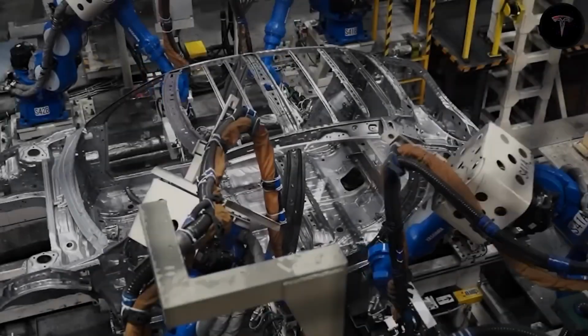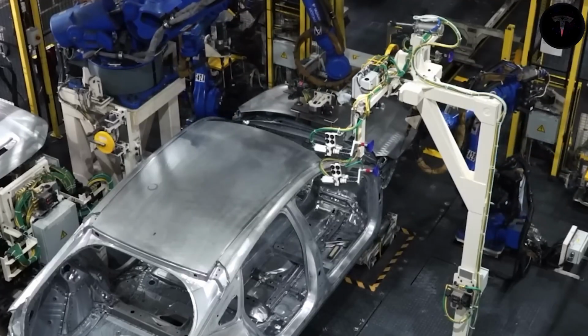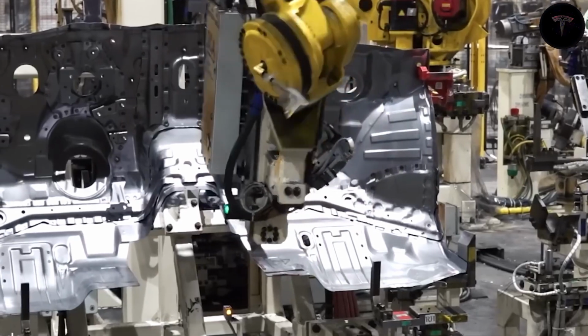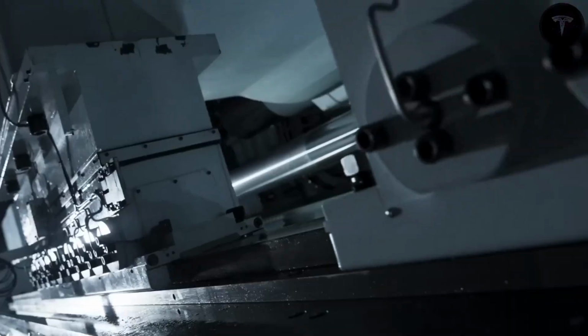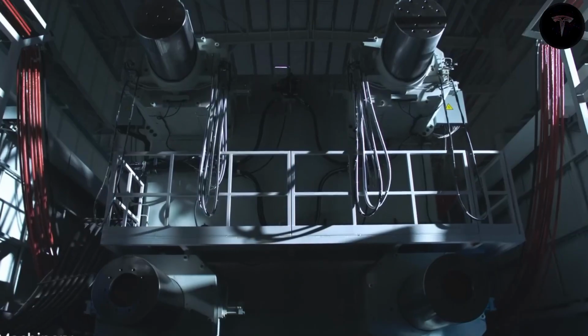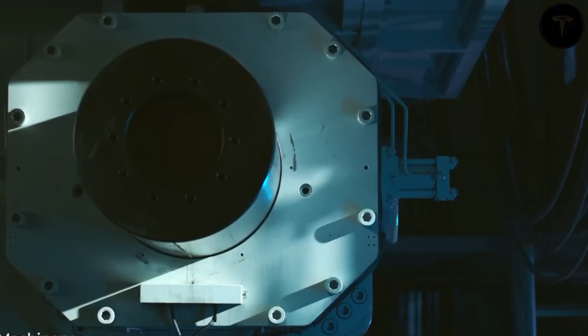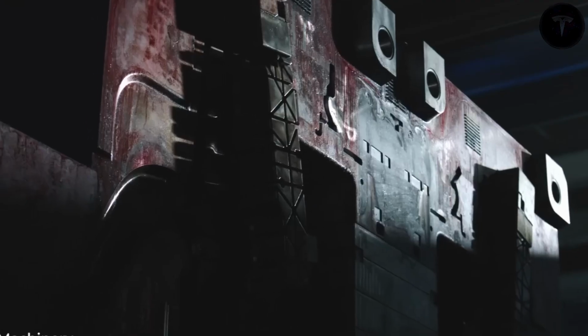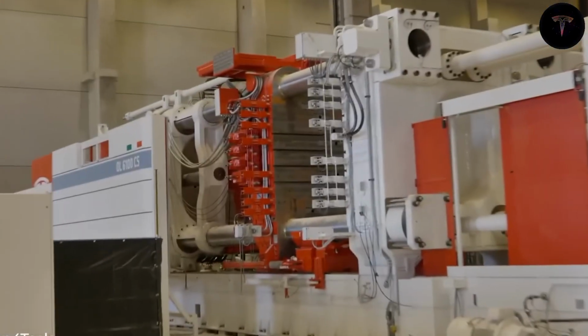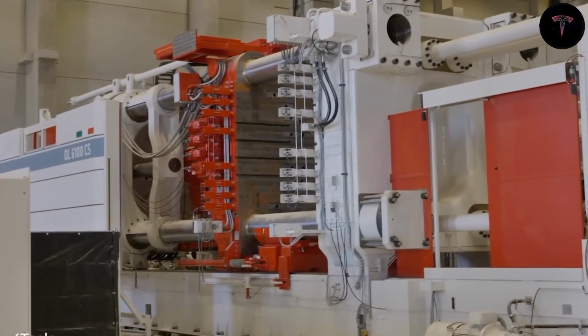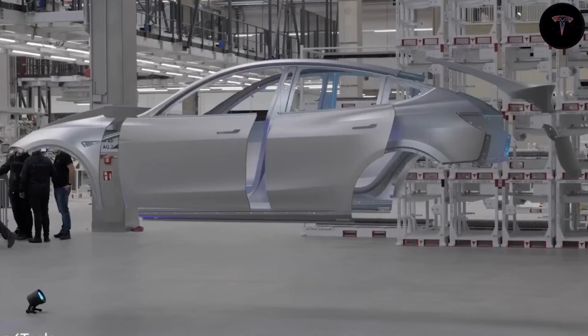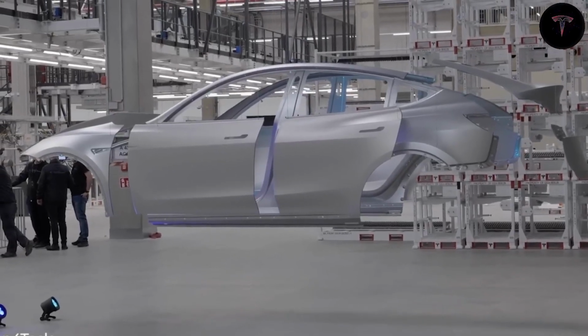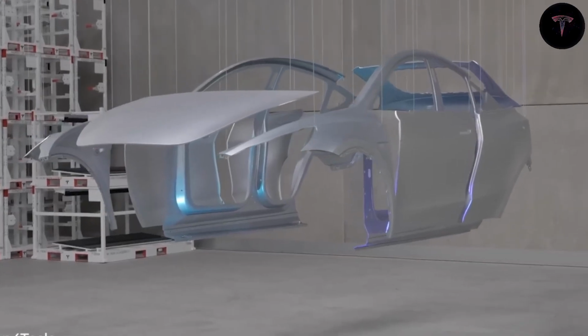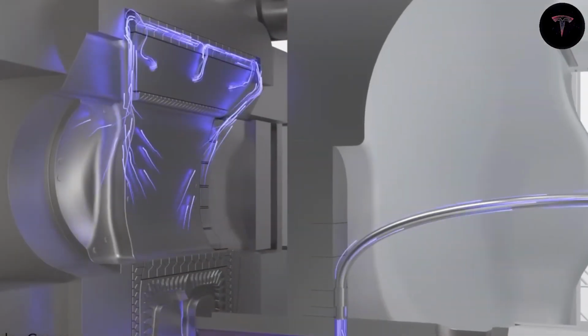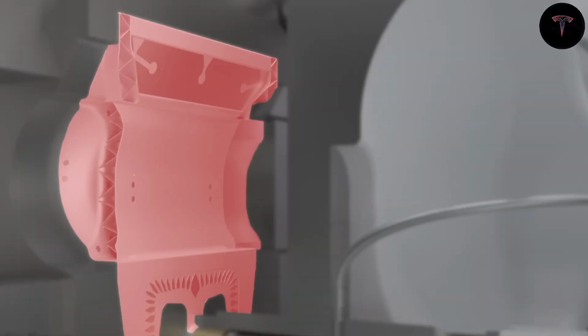Microscopic variation at that scale creates porosity, hot cracking, or internal stress that ruins the part entirely, which is why Tesla has poured resources into proprietary aluminum alloys built specifically for ultra-large structural castings. Alloys engineered for high strength immediately after casting while minimizing distortion and cracking as they cool. Without that materials work, jumping from today's 9,000-ton machines to a future 50,000-ton system would be essentially impossible. The press is just the hardware. The real breakthrough is the metallurgy that makes a machine that size conceivable at all.